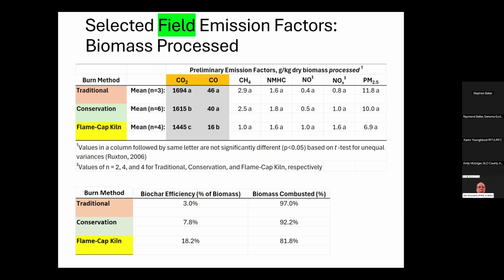And if you look at the bottom, I just give you an idea of what we're talking about here. The traditional burn had about 3% of the original biomass end up as biochar at the end of the experiment. For the conservation burn, that was about 7.8%, and for the flame cap kiln, it was about 18%. So that's what we call biochar efficiency: what fraction of the biomass ended up in the biochar? And you can see the inverse of that, subtracting it from 100%: the fraction of biomass that was combusted, 97% for the traditional, 92% for conservation, and about 82% for the flame cap kiln.